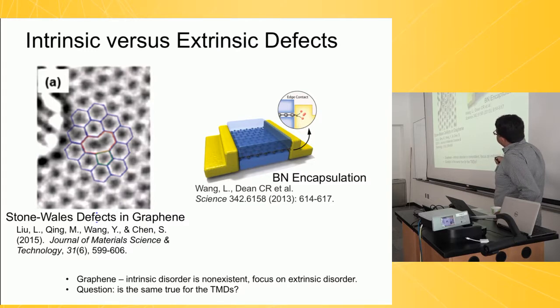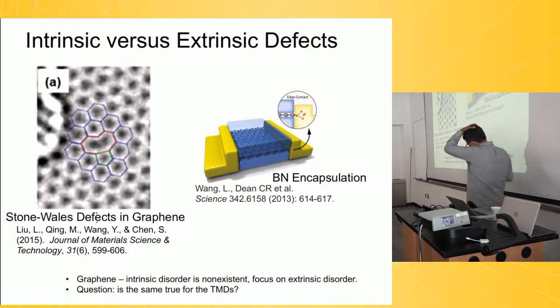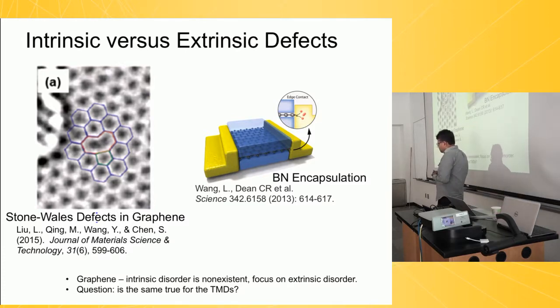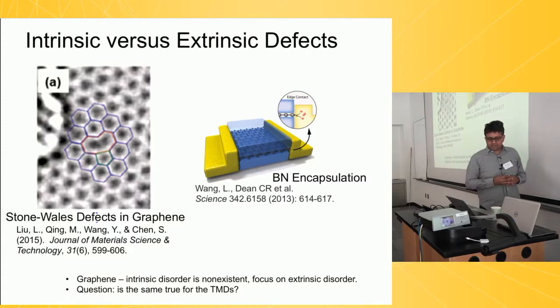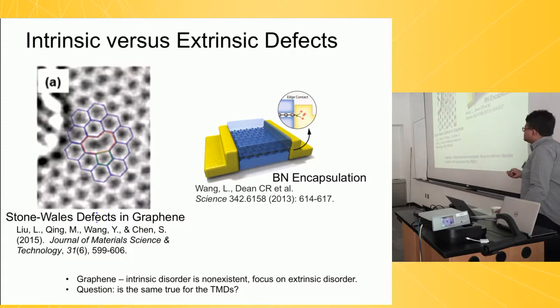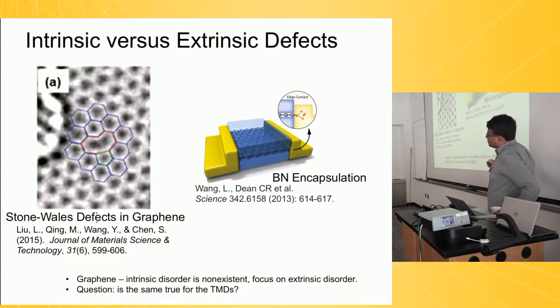Now, as it turns out, in graphene, these are extraordinarily rare. If you take a piece of graphene that's 1 micron square, on average, you have 3 to 4 of these defects. So for all practical purposes, people have just ignored them. Graphene is sort of a perfect material.